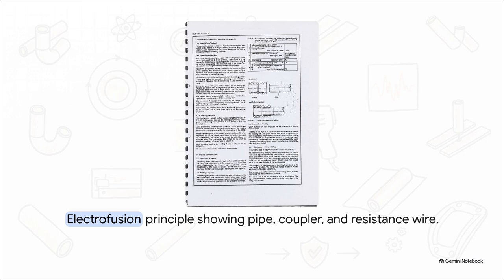You've got the resistance wire seated right between the coupler and the pipe. When energized, that heated wire causes plastification of the surrounding polyethylene. Now, because the fitting itself is rigid, the physical expansion of this molten material gets trapped, and that generates the essential joining pressure between the pipe and the fitting. You don't need massive external hydraulic rams here. The thermodynamics of the expanding polymer volume provide the exact pressure required to forge the weld.